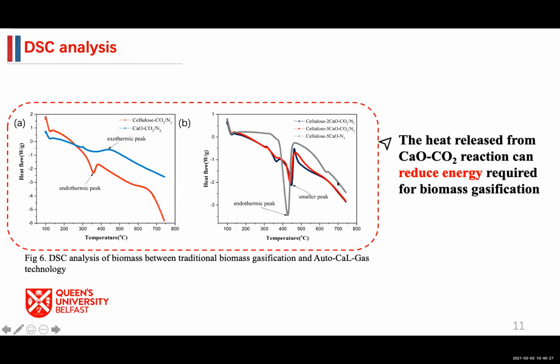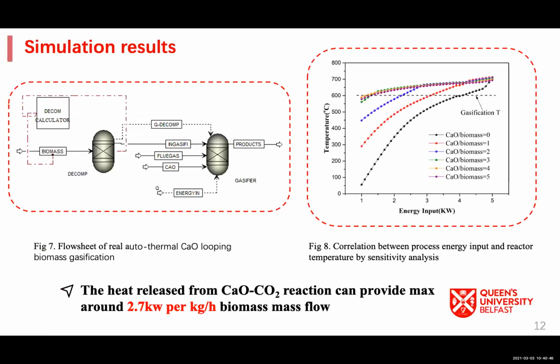And as you can see from figure B, compared with traditional biomass gasification and the nitrogen atmosphere, our process can achieve a smaller endothermic peak, which fundamentally proves that the heat released from calcium oxide carbonation can reduce energy required for biomass gasification.